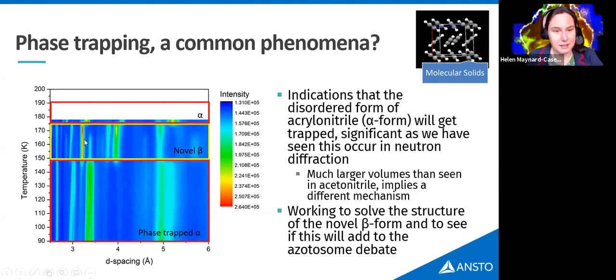So I actually think that this beta form, so this outer, we've started naming it, this alpha form is that same disordered high temperature form. We've discovered this beta form, which I believe is the low temperature form, but the awkward thing is we get the alpha form forming at the low temperatures as well. And the interesting thing is this has happened in our neutron diffraction data. So this is a much bigger sample.